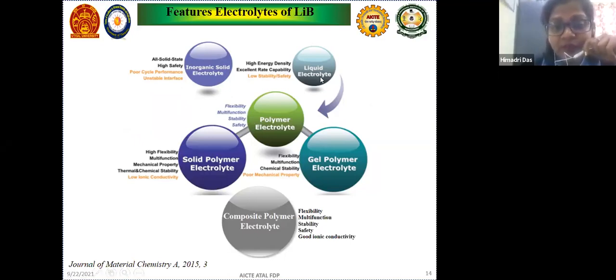And when you go for liquid electrolyte, as I already mentioned, excellent rate capability is found, but stability and safety are very poor because there is a problem of leakage and all. So in the current few decades, people have focused on polymer electrolyte. With polymer electrolyte, we can really go for flexible devices, which are very important nowadays for biomedical applications or smart watches. But the issues with polymer electrolyte are poor mechanical stability, because when we make it flexible, mechanical stability is a major point, as well as low ionic conductivity.